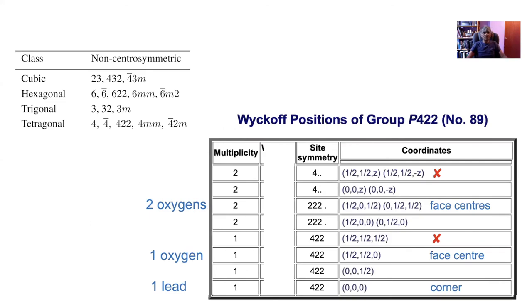So here is our crystallographic table. All these, as I said to you, have been worked out, and you can find them on the web or in standard tables. So this is now for the tetragonal primitive structure with a point group 422. Well, I can actually place a lead atom exactly at the corner. So there's just one lead atom. I can place an oxygen atom at a face center and another two oxygen atoms at other face centers, so